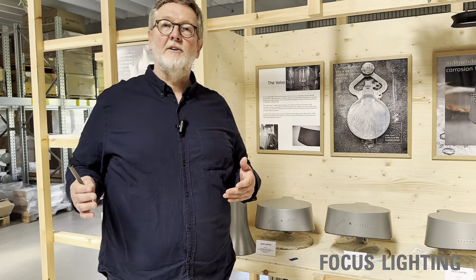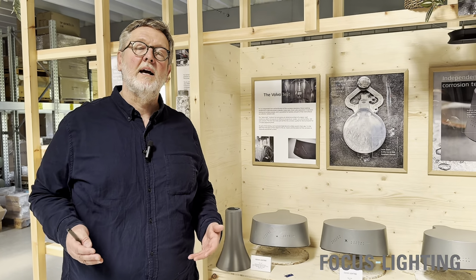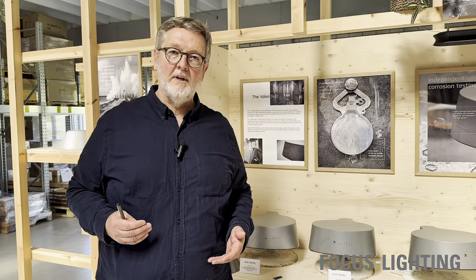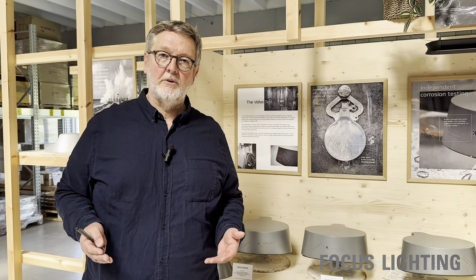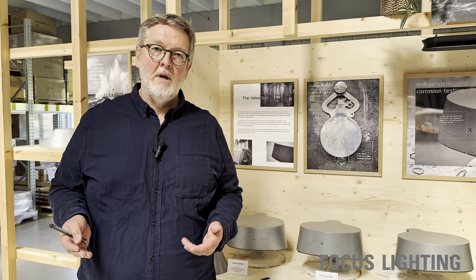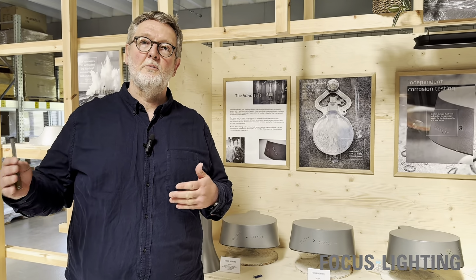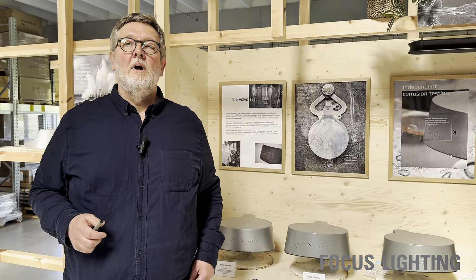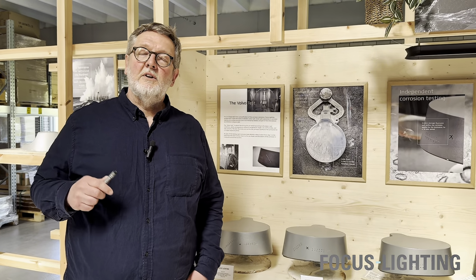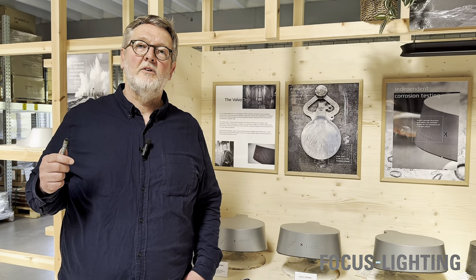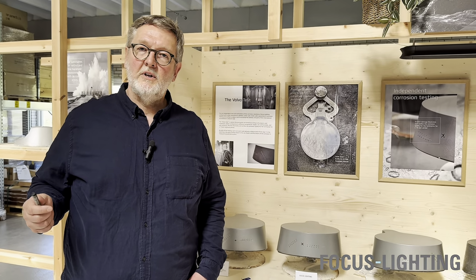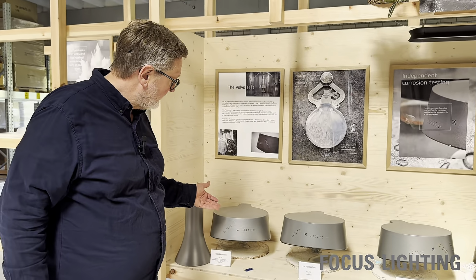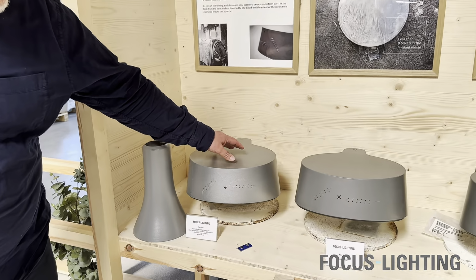In order to verify if we are good, we took these luminaires that we make today and one example of what we made previously. We took that to a test laboratory in Sweden called Proton Laboratory and had them perform a so-called Volvo test, which actually comes from the manufacturer of trucks. And we made a test where we resembled a 10-year endurance test in a road environment. So what we did was, at first we had a look at the sample that was produced 10 years ago.